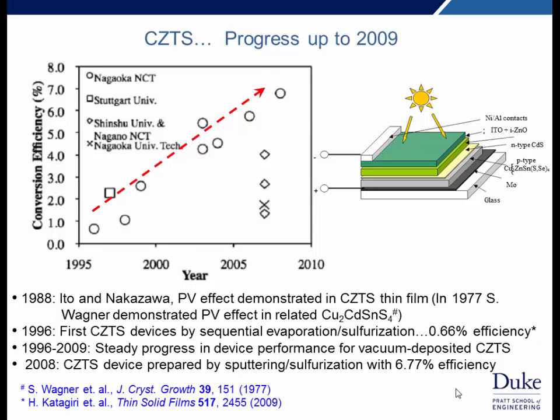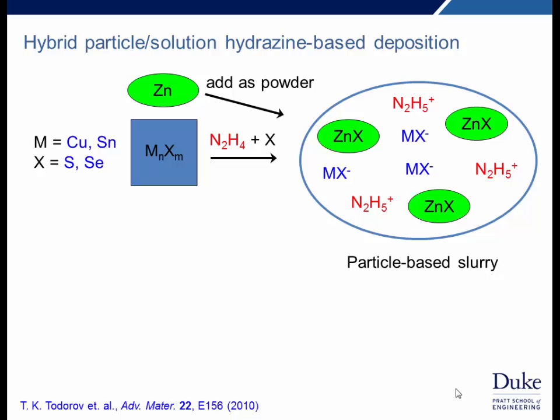And we wanted to see if we could adopt our solution-based approach for doing this. And the problem we ran into was that zinc is not soluble in hydrazine. And so we needed to adopt a hybrid approach in which we first dissolve copper, tin, sulfur, and selenium in hydrazine, and then add zinc powder, which reacts in situ to form these zinc chalcogenide nanoparticles.